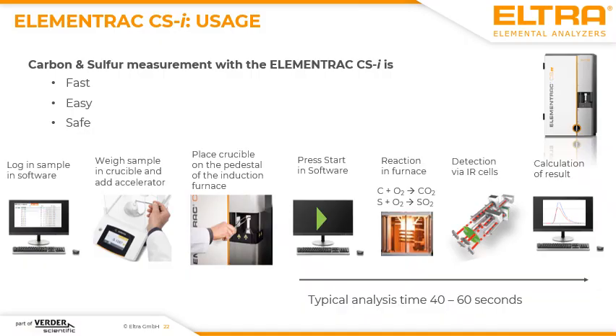But again, we also have to consider the sample shape when we are going to the burning process of the sample, because the more finely divided a powder is, the more trouble you may get with incomplete combustion. There I can provide you some general typical sample weights and accelerators which are suitable to avoid swirling of the sample. Detection of the gases and calculation of results is more or less not dependent on the sample shape, and here we would not expect any technical issues.